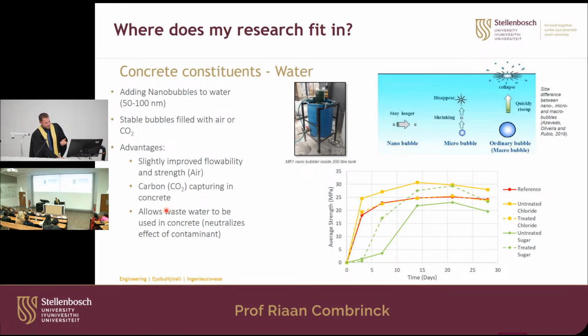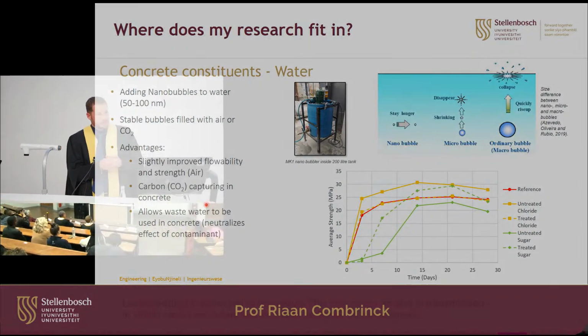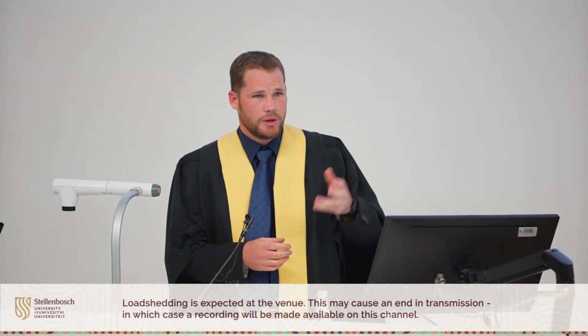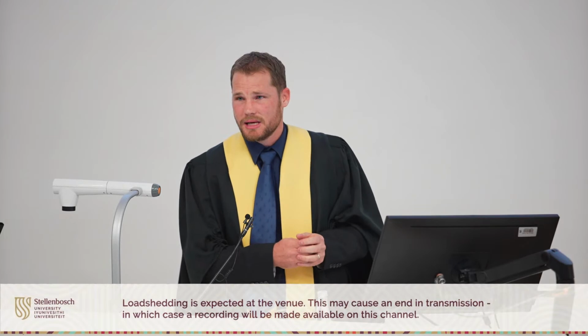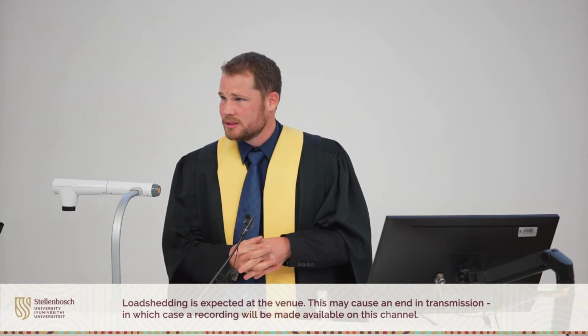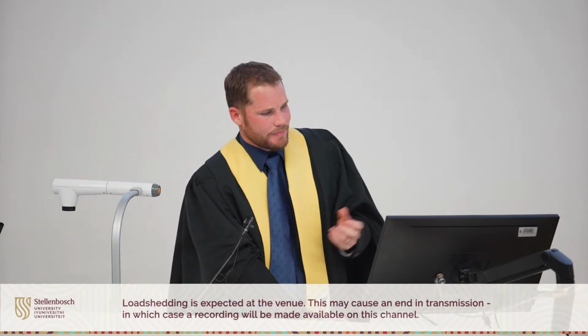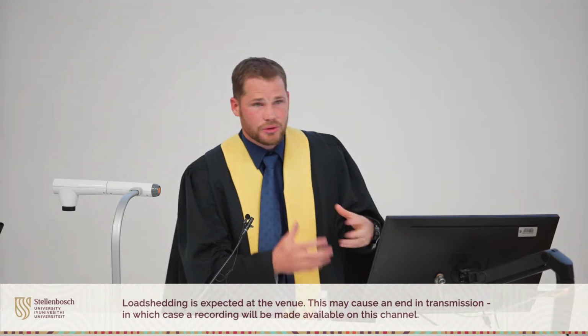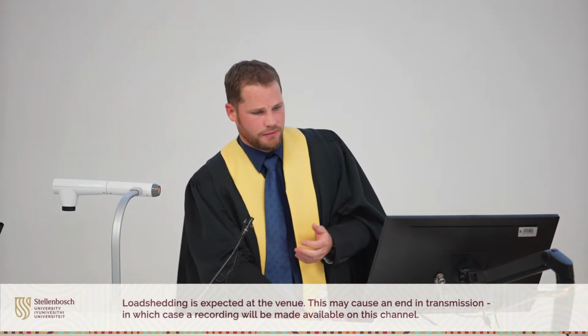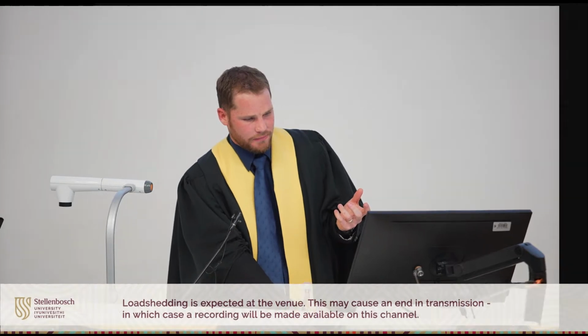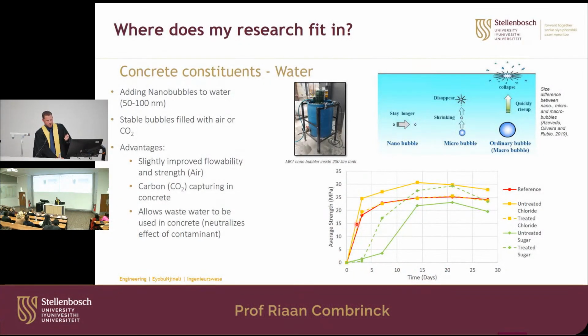And then one I'm very excited about is the use of wastewater. As an application, if you're building a structure far away from potable water, you can use the water that is available there, the brackish water or the borehole water. You can treat it with these nanobubbles, and then you can actually use it, and there we save our precious drinking water. We found that these nanobubbles actually neutralize the effect of the contaminant. If you think of salt, this is the strength with time, and you can see salt, which is chloride, often found in brackish waters, is an accelerator.